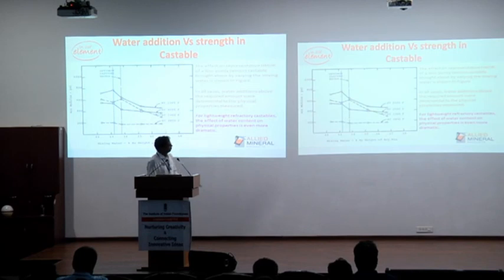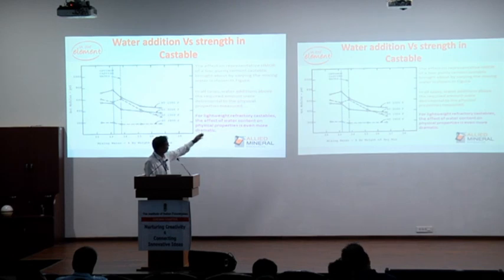So this is a small slide I kept. Whenever we are trying to use a castable, we have to take care of the water percentage, because there's always a recommendation given by the manufacturer about the water percentage. If you go beyond the limited water percentage, then you will lose strength drastically. You can see the hot modulus of rupture here, and the mixing by weight. This optimum casting water is a range you can go up to at maximum, otherwise you can see the strength drastically falling down.